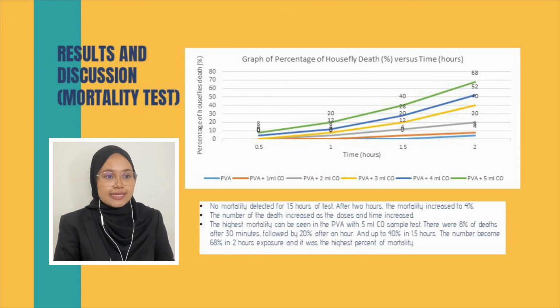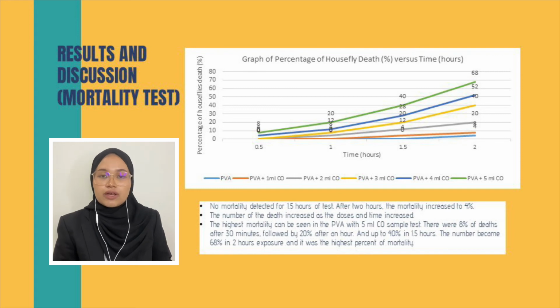The mortality test can be seen in the graph. There is no mortality detected for 1.5 hours of the test. After 2 hours, the mortality increased to 4%. And then the number of deaths increased as the dose and time increased. The highest mortality can be seen in the PVA with 5 ml CO, which were 8% deaths after 30 minutes, followed by 20% after 1 hour, and then up to 40% in 1.5 hours, and then the number becomes 68% in 2 hours exposure, which was the highest percent of mortality.